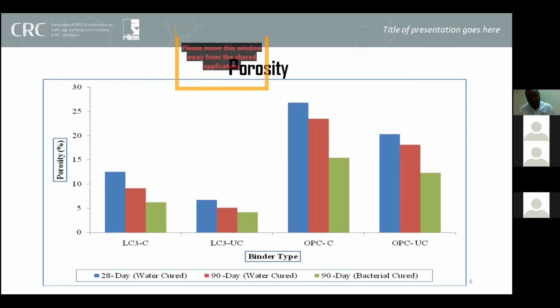The difference can be attributed to the fact that in bacterial solution, we have precipitation of calcium carbonate from the bacteria, which results in sealing of the cracks. When the cracks are sealed, the material becomes less porous.